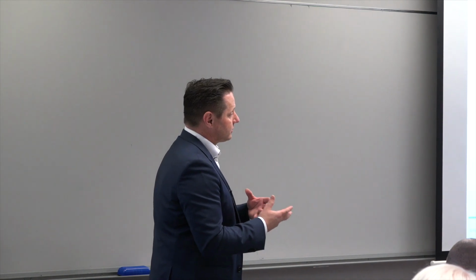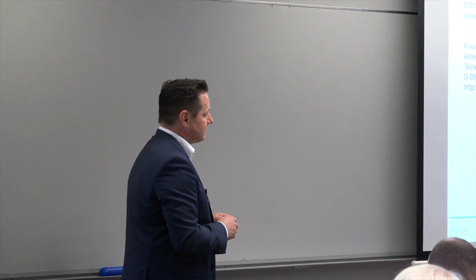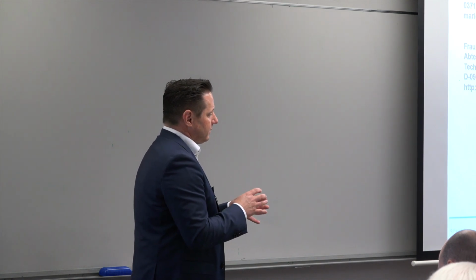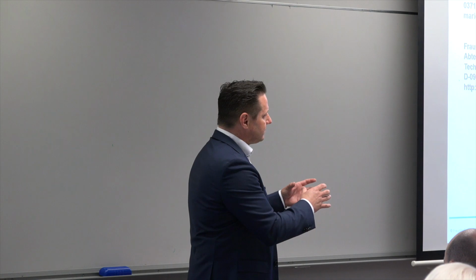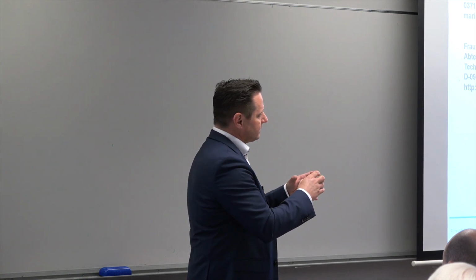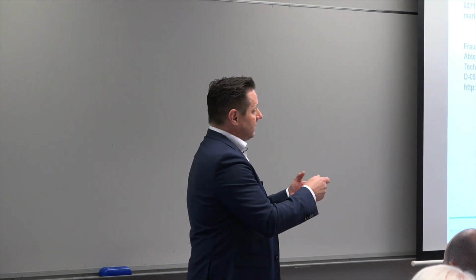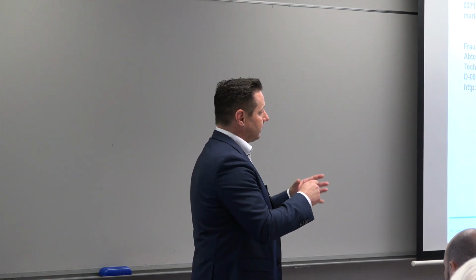Exactly, the stretchable part of this idea is the open point, where we are also looking for substrates. We have some ideas looking at silicones or some other materials, but the problem is the combination with the printing technologies and also some other deposition technologies. Parylene is one of the base materials where we can combine the semiconductor-like or wafer-based technologies with this kind of flexible substrate by using a sacrificial layer. That means we are using a rigid silicon wafer, having the parylene on top, and can handle this system by printing, by depositing, by sputtering, etching. So it's almost compatible with all the semiconductor processes.